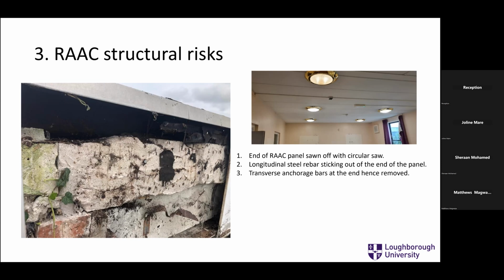So we've taken the fascia off, and that's quite a deep 200 mil deep RAAC panel sat on a concrete ring beam. Okay, so not too bad, but you'll see some dots, and that's the steel sticking out the end. And you'll see almost some circles. So this is where someone's going to use a circular saw and cut off the end of the panel to make it fit the size of the room. Okay, but what they've done is they've sawn through the steel. They've sawn through the end of the longitudinal steel. So you've got no cover. So in worst cases, then water can get to it, it can corrode.